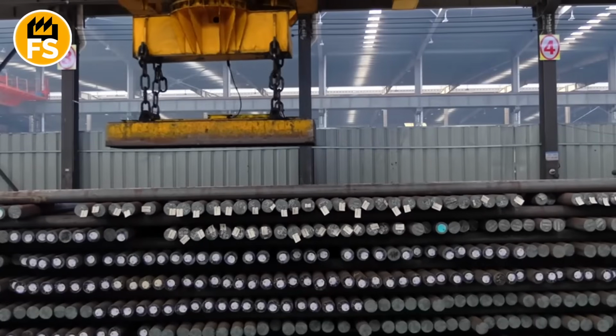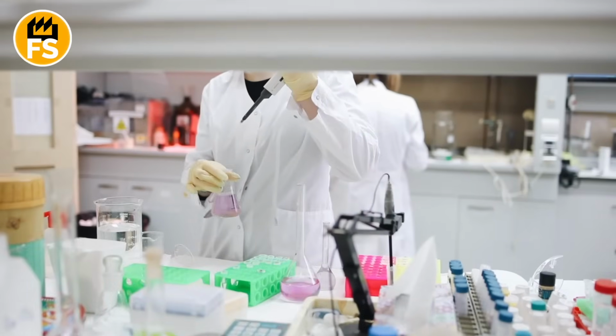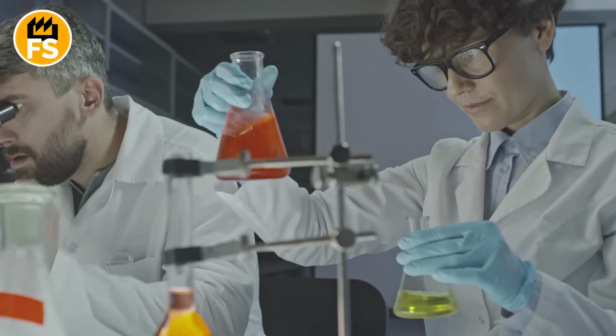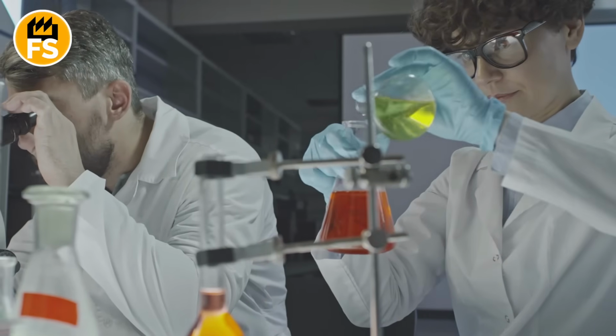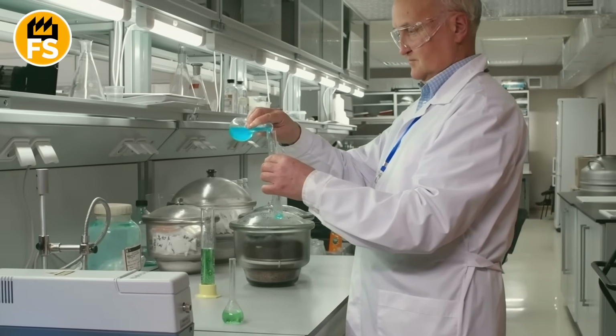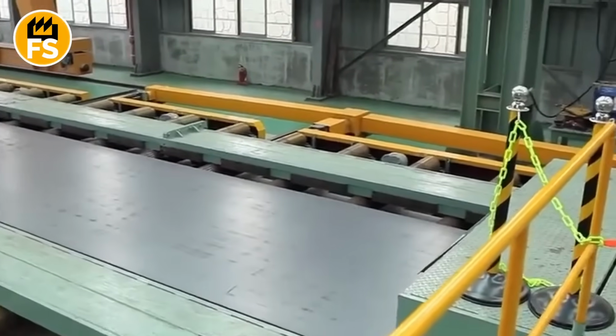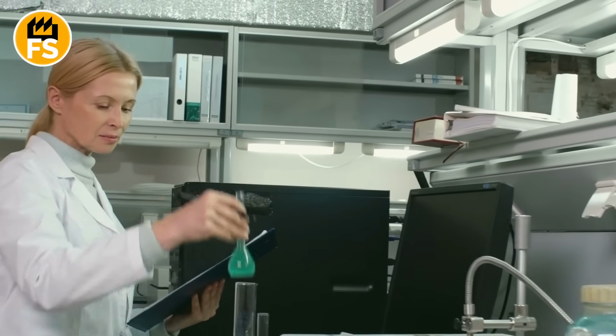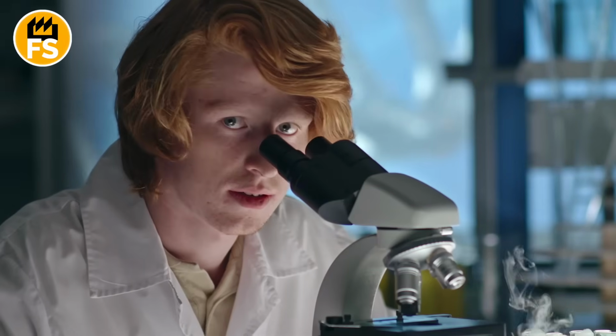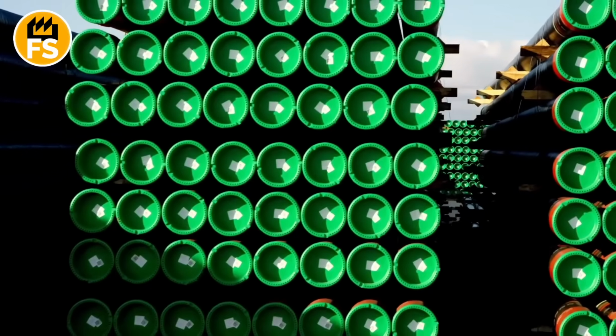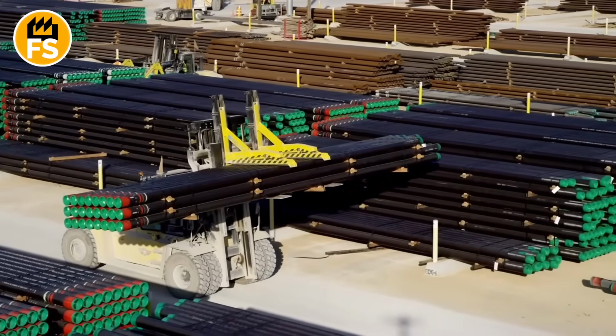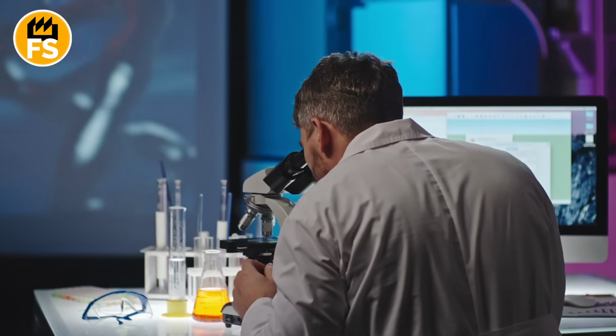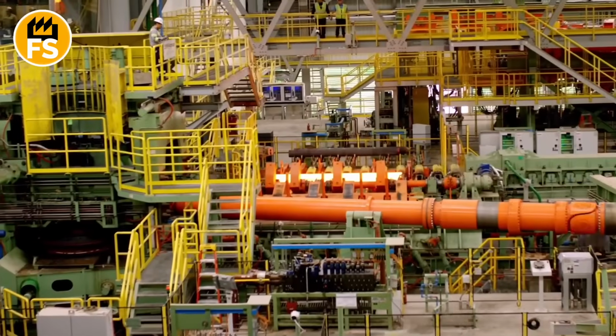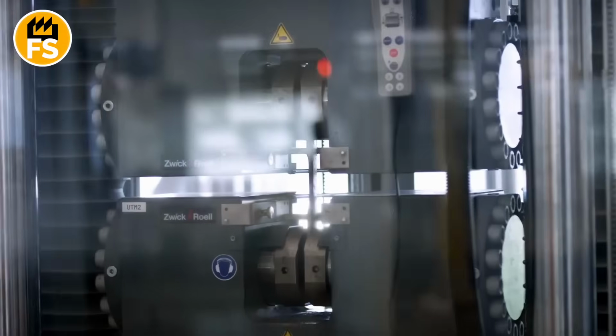Next comes the chemical analysis. For this, 5 or 10 metal samples are taken from each batch and sent to the factory laboratory. There, they use special spectrometers, devices that read the metal's composition using light emissions. The spectrometer determines over 12 elements in the composition in seconds. During the analysis, the sample is treated with an electric spark or a laser. This excites the atoms on the metal surface, causing them to emit light of different wavelengths. Each chemical element glows uniquely, so the device recognizes exactly which elements are present in the steel and in what quantities. How much carbon, manganese, chromium, nickel, or phosphorus. This analysis takes only a few minutes, but provides a complete picture of how well the billet meets technical requirements.